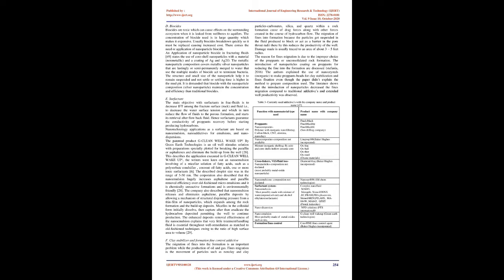It has been explained in the research paper 47 that nanoparticles have the ability to improve and stabilize viscosity when mixed with VES fluids, and this process is called pseudo-cross-linking. It is the phenomenon of the creation of a three-dimensional network in micellar solution. The nanoparticle acts as a physical cross-linker by the creation of micelle-nanoparticle junctions. In this way, addition of nanoparticles in VES fluids increases and maintains the viscosity at higher temperatures, thereby reducing the fluid loss in the rock formation. 51 states Guar gum gel viscoelastic property is increased when it is cross-linked with nanosilica cross-linker due to increase of intermolecular forces, and the stability of the structure is enhanced by the nano-cross-linker.